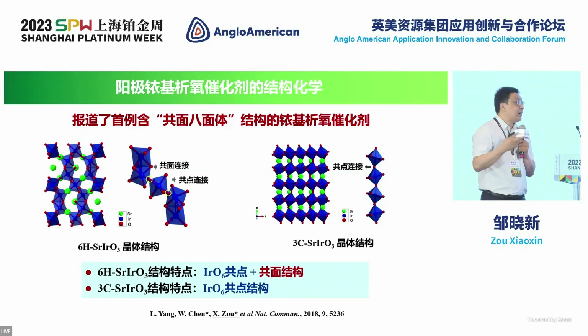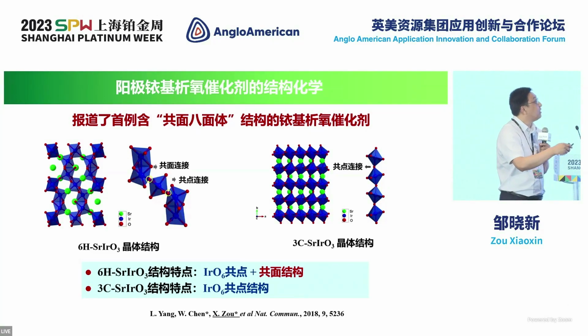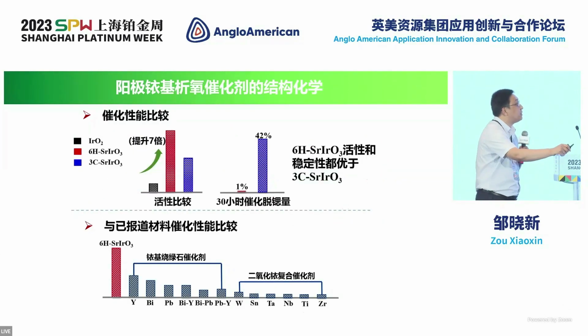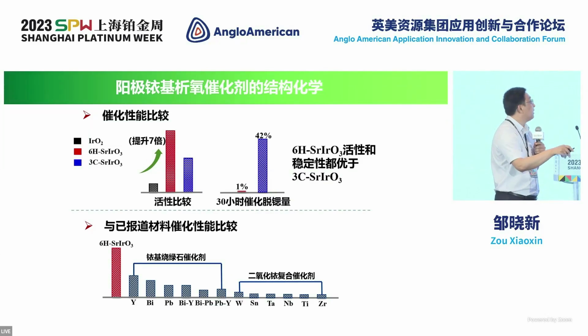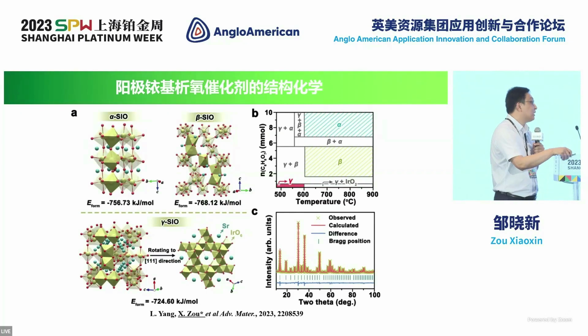SrIrO3 structure. We found that all of the sides have a coplanar connection. From an inorganic chemistry point of view, that's really rare. So we are actually the first example to have this coplanar connection. With this coplanar connection, in terms of both activity and stability, it is much better than iridium dioxide, and also better than 3C SrIrO3.